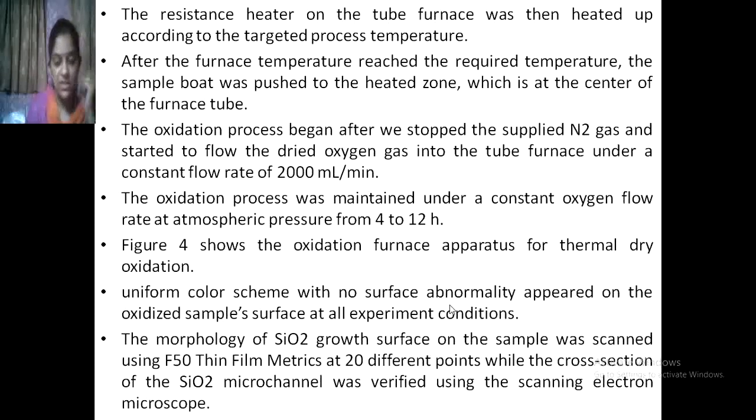And how is it tested, whether it is the correct one or not? The morphology of the SiO2 growth surface on the sample was scanned using F50 Thin Film Metrics at 20 different points, while the cross section of the SiO2 microchannel was verified using the scanning electron microscope.